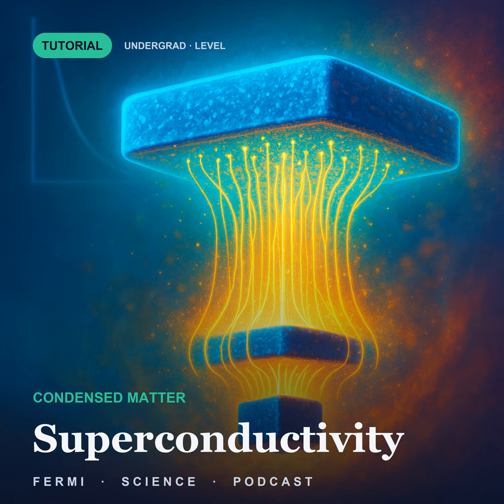4 of them, and none is a matter of adjusting a coefficient. The transition temperatures are far above anything the phonons of a copper oxide can produce. The frequencies are measured, the couplings are measured, and no exponential you're entitled to write gets you to 93.